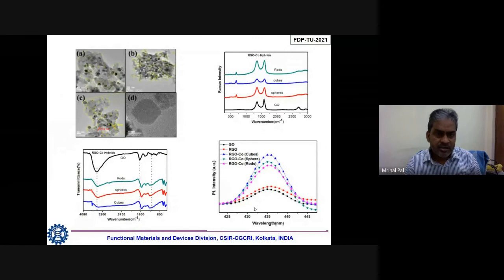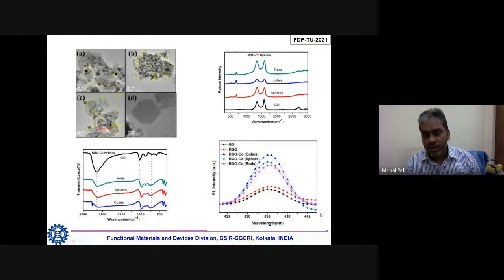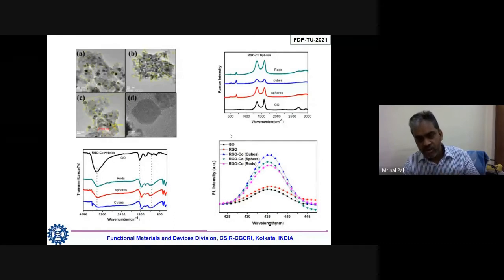Here again we have prepared similar cube nanoparticles and rods of cobalt, and ultimately we have shown that it is possible to enhance the blue emission for different morphology. And you can see that in the case of this cube, where cobalt nanocubes are decorated in the graphene structure, we can get maximum blue emission. So that blue emission can be tuned by changing, as I have shown, the morphology or the structure of the cobalt particle which is decorated in the graphene structure.